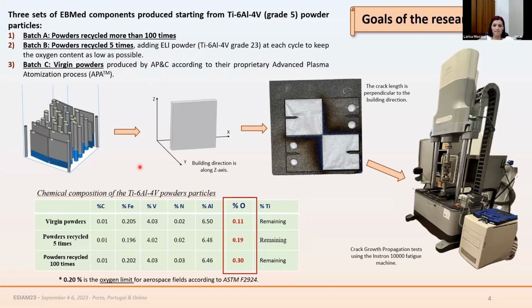And in this work, we focused on these plates here, this plate. And here there is a more detailed view because I wanted to highlight that the building direction is along the z-axis. Then each plate was sectioned in order to obtain 4 compact tension samples for each plate, in order to have the crack length perpendicular to the building direction. And then all of these samples were subjected to the crack growth propagation test using this Instron 10,000 fatigue machine.